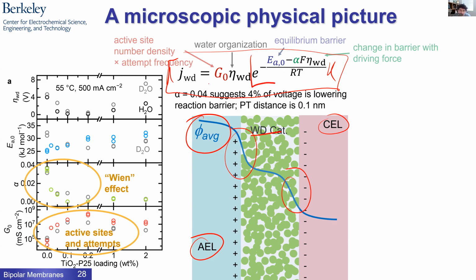So this part here, this is the rate, the current is the rate. This part here is an exponential that depends on the equilibrium barrier for the reaction. And then this part is a commonly used part in electrochemistry to describe how that equilibrium barrier changes as you change the driving force, the voltage driving force, the overpotential in this case for water dissociation. Okay, so if alpha is small, if alpha is 0, there's no effect. If alpha is 1, all the driving force goes into changing the barrier. That's what this exponential says.